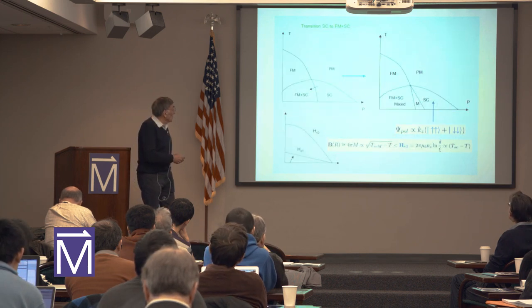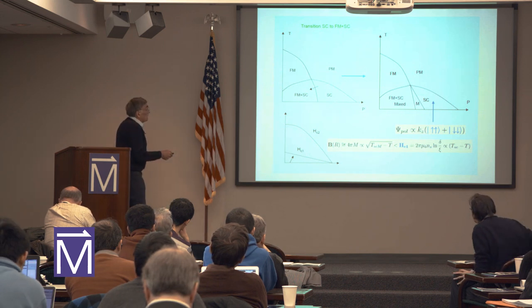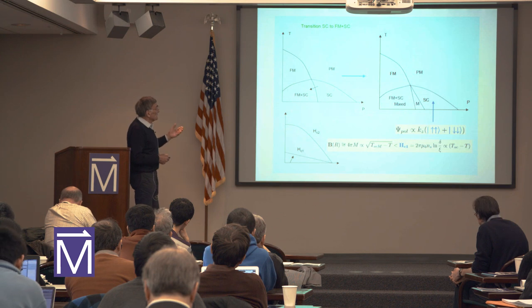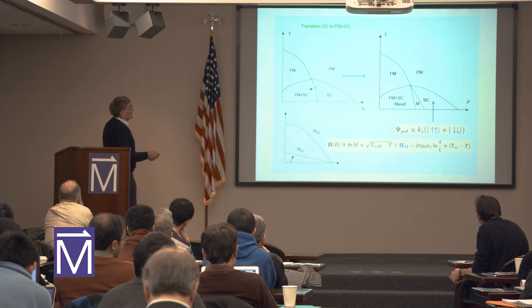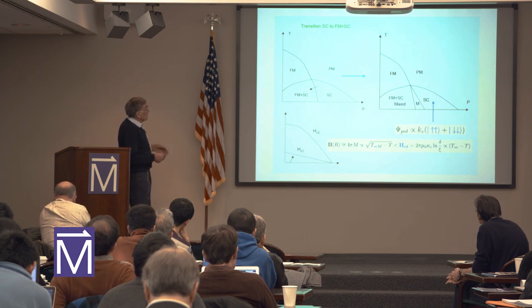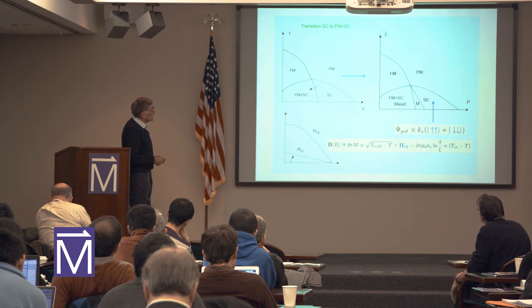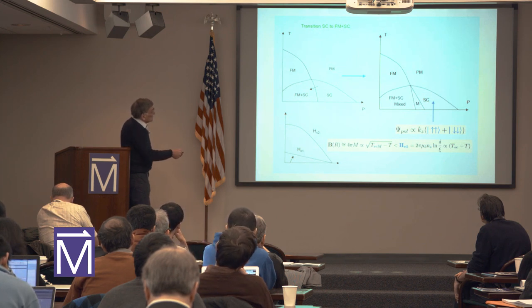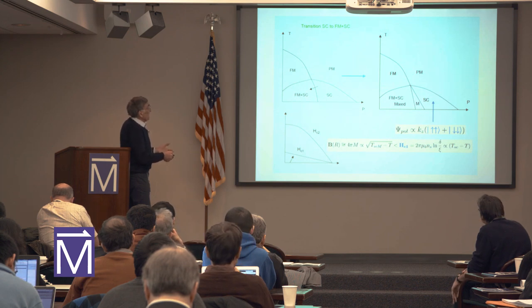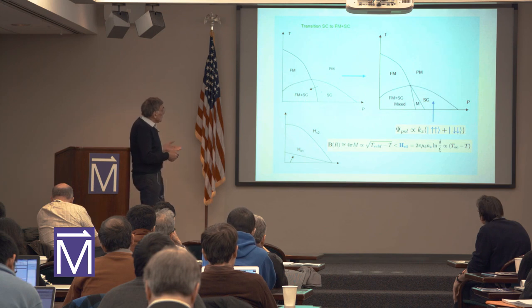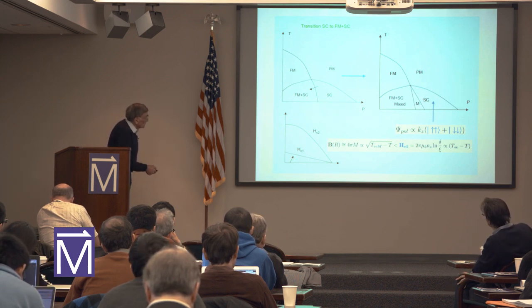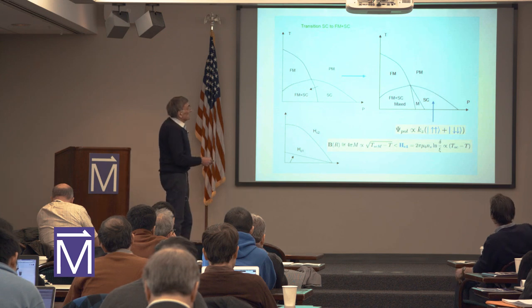Regarding the transition from the paramagnetic superconducting state — any superconducting state is diamagnetic, though paramagnetic in the spin sense — when we go from paramagnetic superconducting to ferromagnetic superconducting and solve this problem for a neutral Fermi liquid, one finds that this phase transition is in fact absent. Because when moving in this direction, one already has a well-developed superconducting state, and going to the ferromagnetic superconducting state one simply passes through the Meissner state. So this transition looks like: you go to the Meissner state, and when you intersect the HC1 line, the transition occurs.